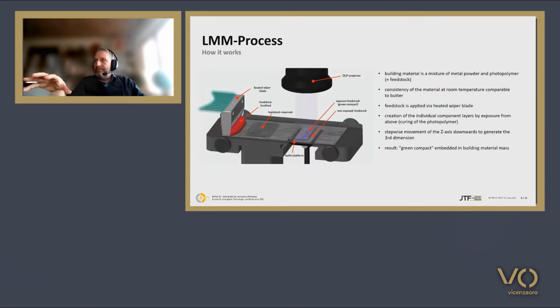So the machine itself looks like you see on the slide, and the material is a very special sauce, we call it. It's a mixture of metal powder and a photopolymer, and the metal filling ratio is between 55 and 60% weight percent of material. The consistency of the whole material is best compared to butter, which means at room temperature, it's solid. If you cool it down, which we do in a printing chamber, it's nearly hard, as it would be a very cool butter block. But if you heat it up over 50 degrees, it gets a very low viscosity, and it's really water-like. And this helps us to apply the material.